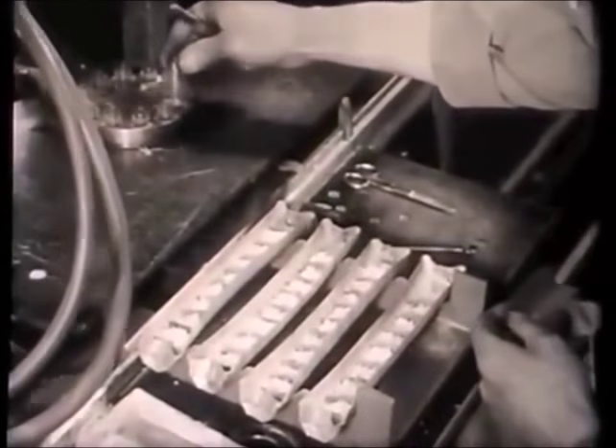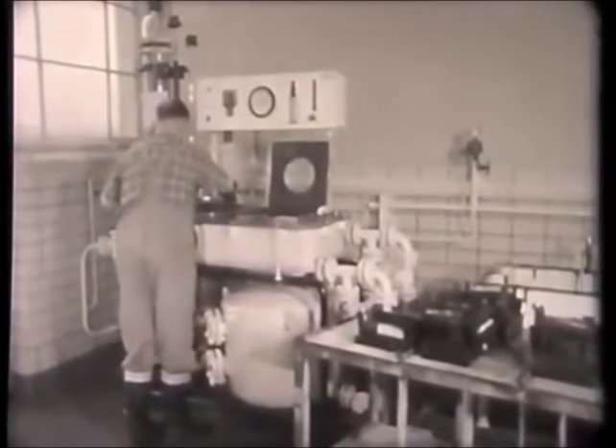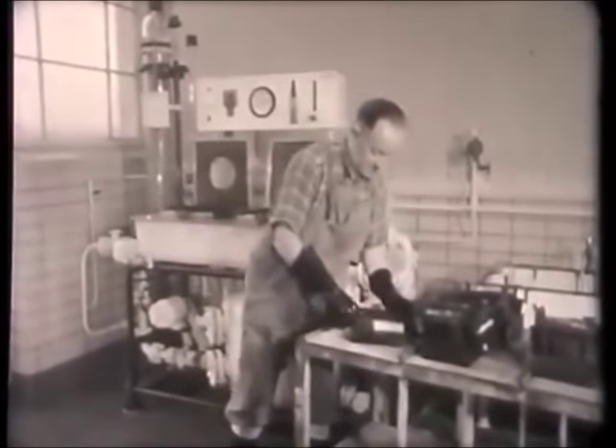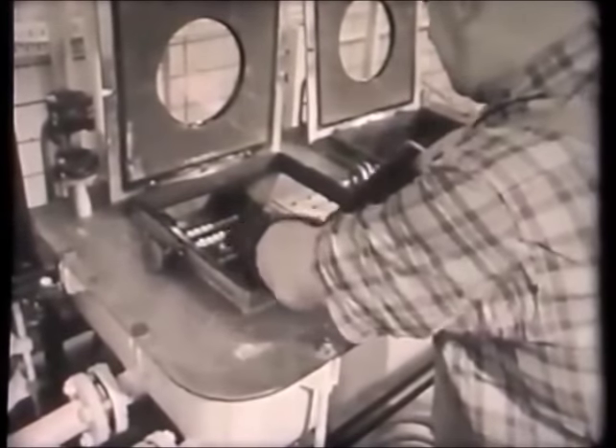You will remember that during the manufacture of the heater wire, the fine tungsten filament was wrapped around a molybdenum core which served as a mandrel during the winding and as a support during the subsequent operations. As this core is no longer required, it is removed by immersing the heaters in a bath of strong acid, which dissolves out the molybdenum, leaving only the coated tungsten spiral.